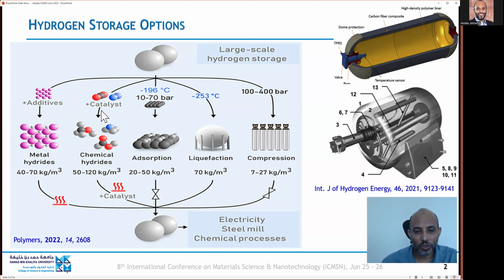Alternatively, we can chemically store hydrogen in chemical compounds, in what we call chemical hydrides, like you can consider ammonia, which has significantly high hydrogen content of 17.7 kilogram per kilogram, providing significantly high energy density. But of course, we need to use catalyst for the formation of the chemical hydrides and then to decompose the chemical hydrides. So this requires also a high temperature for the desorption and high pressure for the formation of the chemical hydrides.